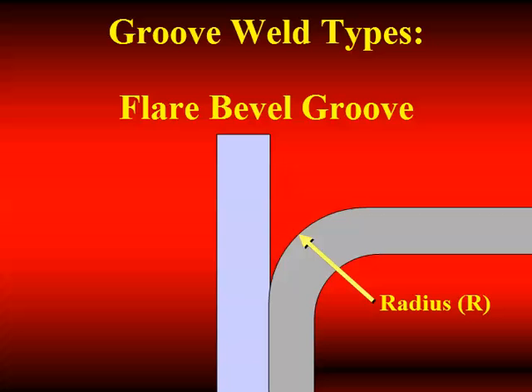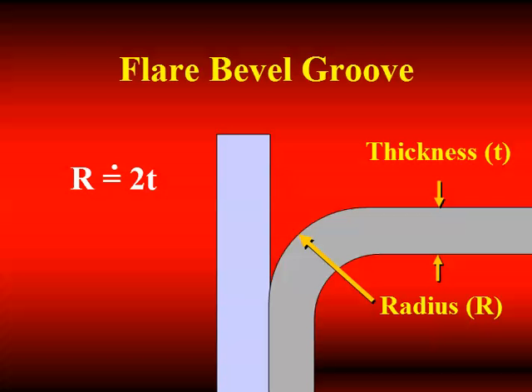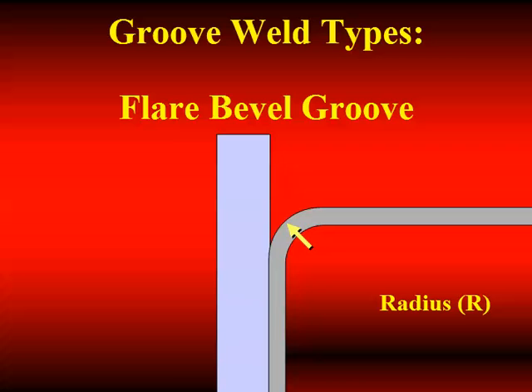Now, I mentioned that the radius is a function of the thickness of the material and generally follows a rough pattern of being 2 times T, but mill practice varies. And you might want to check the radii associated with some of the shapes you're getting if this becomes a critical factor. Now, if your radius is small, then the weld that you put in there is likely to be pretty small, and the throat's going to be small. As the thickness goes up, that radius is going to get larger.